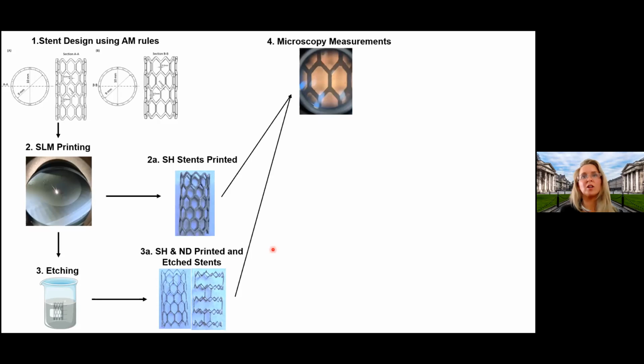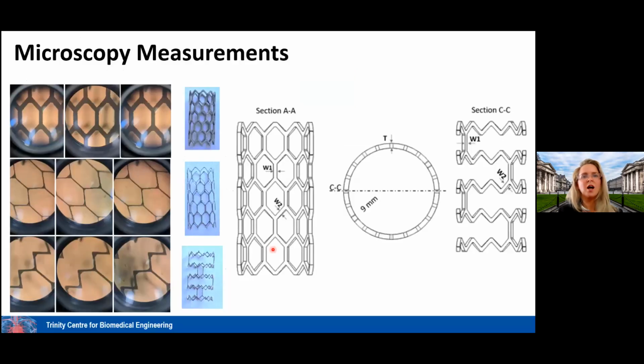Going from there, we then thought, is this stent likely to have any structural integrity after etching? Will it have strut thicknesses and surface finishes similar to those typical of a commercial stent suitable for implantation? And we did that by looking at microscopic measurements of the stent.